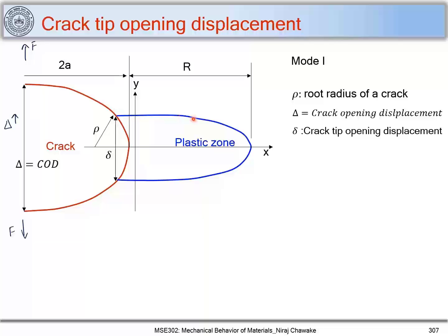Now what you can consider is that this is a plastic zone. So ahead of this crack tip, you can consider that there is a tensile sample or specimen which has dimensions of length L and width W. So you can say that when the force is applied, this sample, that is a tensile sample, will experience some kind of plastic strain, because this lies in the plastic zone, and that's why this sample will elongate, and that is how this delta is modeled based on the strain developed in this tensile sample. So this is an imaginary situation or just a thought experiment that there is a series of this kind of tensile samples ahead of this crack tip which can represent this plastic zone.